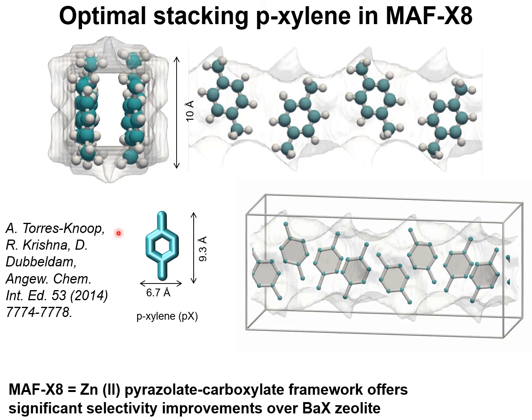For optimal stacking of para-xylene within an adsorbent, we need channel dimensions which are about 10 angstrom so that para-xylenes can stack vertically.